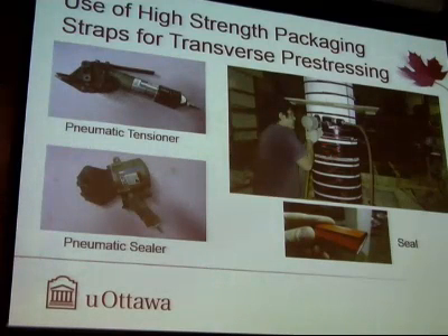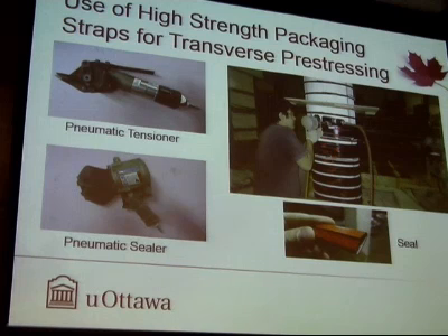Now, more recently, because of the special skills required for pre-stressing columns, we tried to use high-strength packaging straps to see if we can simplify this procedure. After all, we need lateral pressure and we need high-strength steel. The packaging straps that we typically use have up to 800 MPa strength, and they come with handheld devices, and you can pull them and pre-stress them, and then they use what is known as seals to anchor them.